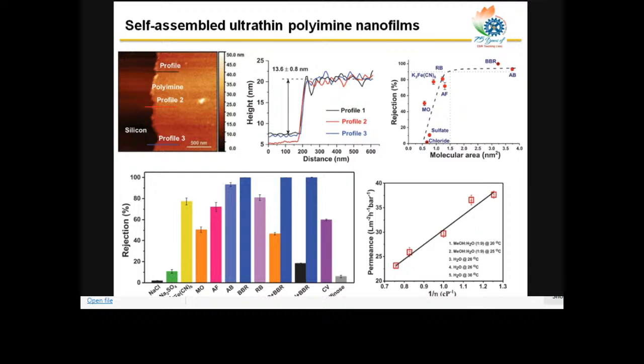And on the top right, you can see the molecular area versus rejection property. That means depending on the molecular size, you get the rejection. So if you want to separate sulfate or chloride ions from a molecule, let's say BBR, that means brilliant blue R, you can see the brilliant blue R has almost 100% rejection, where the sulfate or chloride ion can happily go through the membrane. So we can eventually have a very nice separation between brilliant blue R and salt.